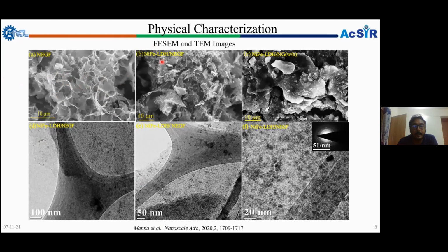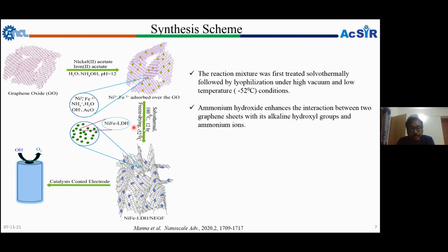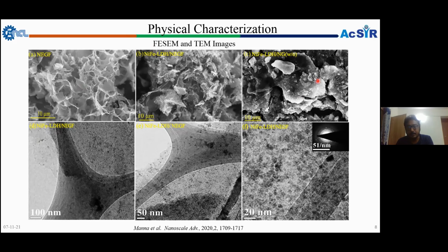In the presence of nickel iron layered double hydroxide, a similar morphology is formed, porosity is also retained, and the entangled structure is formed. But as I already told, there is an importance of the freeze drying method. So here we did it without freeze drying, applying just direct filtration of this material. We avoided these steps. Just after the solvothermal treatment, we went for filtration and removed the water. So there is a stacked nature of the graphene sheets formed. So we found the importance of the freeze drying method to form the 3D structure of the graphene and supported nickel iron layered double hydroxide.